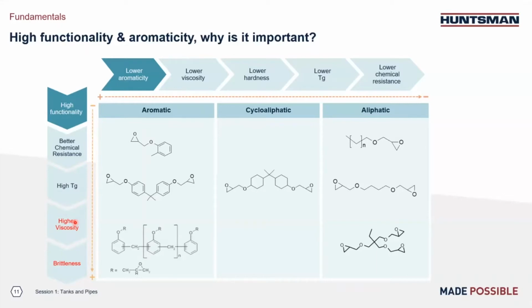On the other side, if we move epoxy resin from aromatic to cycloaliphatic all the way to aliphatic type, we have lower hardness development, and we will also reduce the Tg, which will impact the chemical resistance. But in return, we have lower viscosity, better flexibility, and also better UV resistance. So you always want to take the right resin for your end application. So for heavy-duty applications, a lot of times we want to choose high functionality epoxy resins.